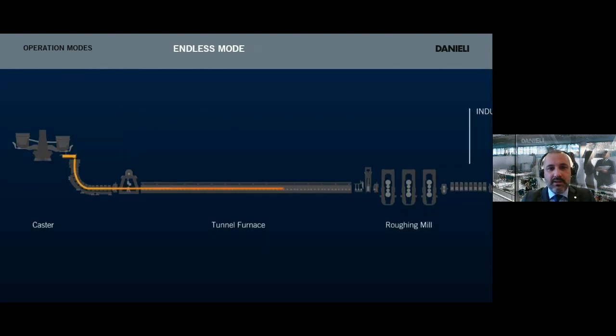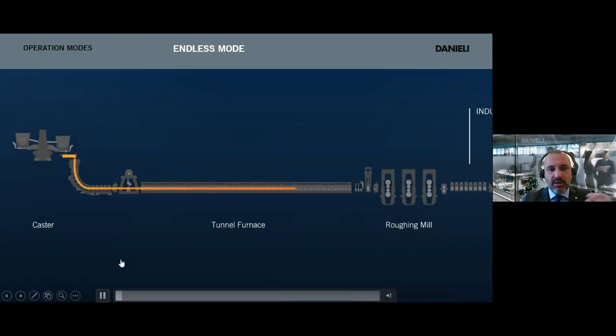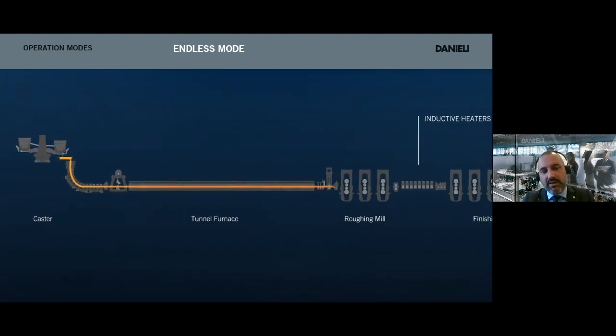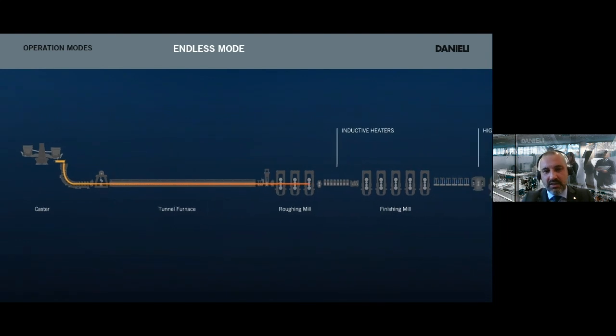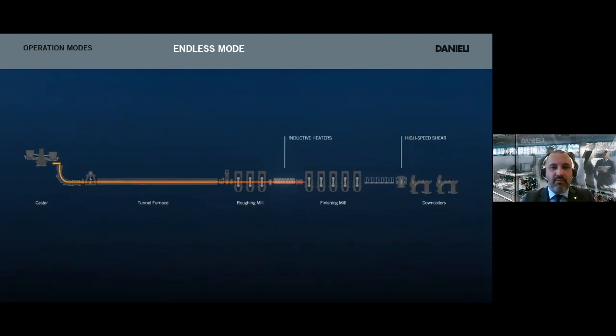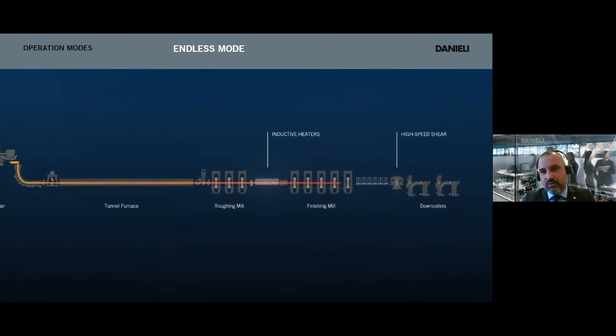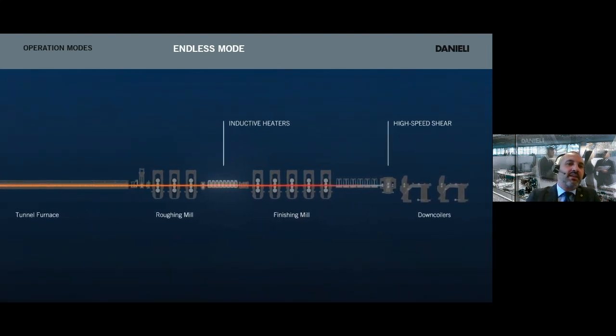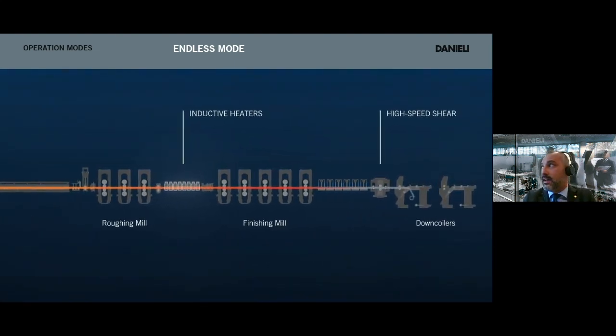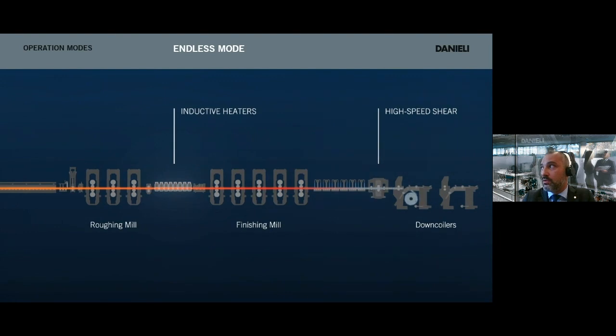And finally, the pure endless mode. So pure endless mode is now becoming more and more familiar to everybody. In this case, there is an uninterrupted slab from caster down to the coiler with an intermediate reheating in the rolling area thanks to induction heating system. And the slab and the coils are cut to length with the high-speed shear. In this case, we can perform thin and ultra thin gauge production.